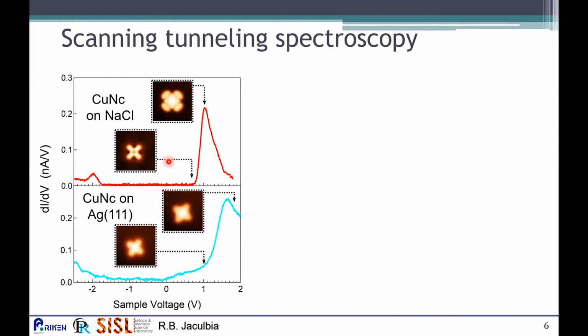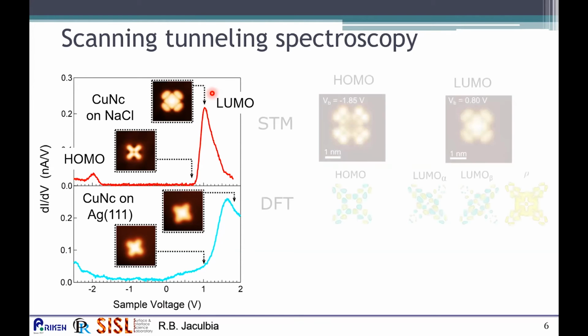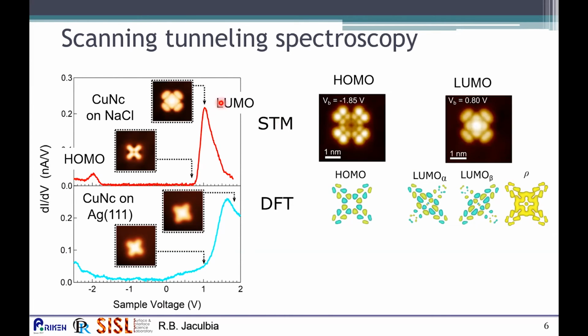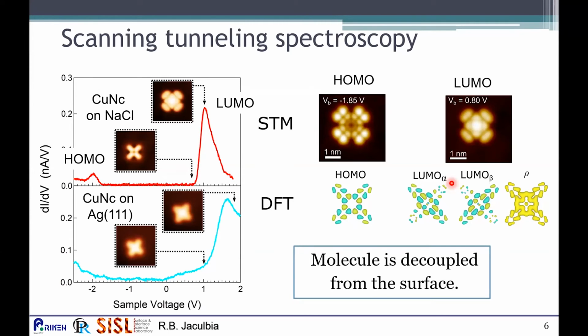Moreover, when we adjust the STM scanning conditions, we have found obvious change in the STM topography of the molecule in the in-gap state and on the LUMO of the molecule. And in fact, by comparing with DFT calculations, we know that when we scan the molecule using STM at these bias voltages, we can observe different HOMO and LUMO topographies, and these topographies nicely match the DFT calculated molecular orbitals. These results clearly show that the molecule is electronically decoupled from the metal surface, unlike when the molecule is on silver 111.